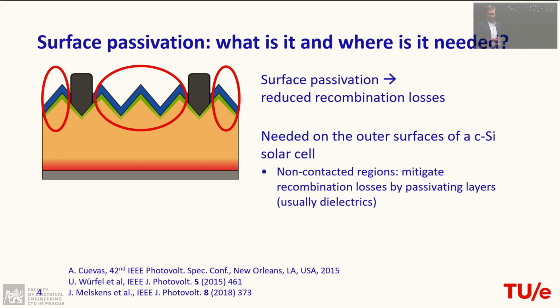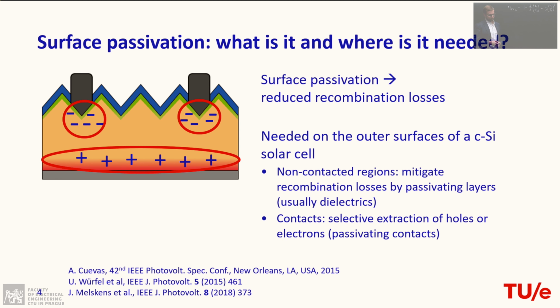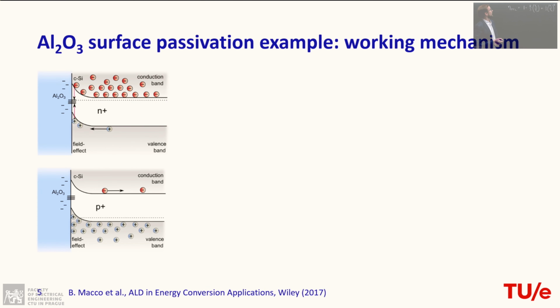And we have these non-contacted regions. And to mitigate these recombination losses, we use passivation layers. Usually these are dielectric materials that are not conductive themselves. Then we also have contacts, and you want to selectively extract your holes or your electrons, and then you get your passivating contacts, as I mentioned earlier. So now we look at one example for p-type surfaces in crystalline silicon, aluminum oxide. This is probably the most common material nowadays to passivate p-type surfaces.